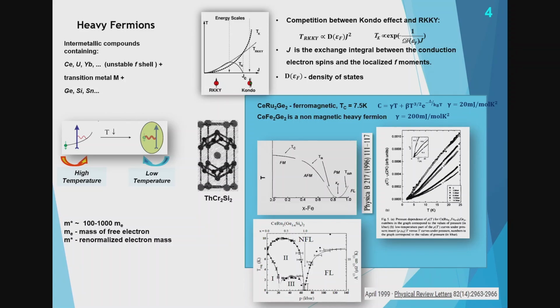And here is just an example. I will show you this picture again. And you see if you stop at 0.8 or 0.9 of iron, with 90%, you can see that this system is already in the quantum critical point. This is the signature of a quantum critical point. The resistivity is linear with the temperature at low temperatures, which is not common in normal metals. In normal metals, you see a quadratic behavior. And if you apply pressure, you go from the quantum critical point to this side, which is the Fermi-liquid behavior already. So we can tune the quantum critical point to the Fermi-liquid region just by applying pressure.